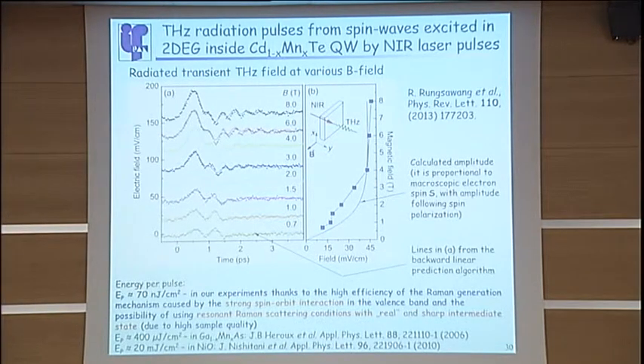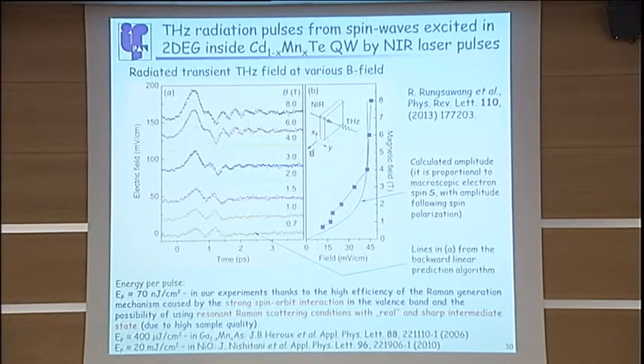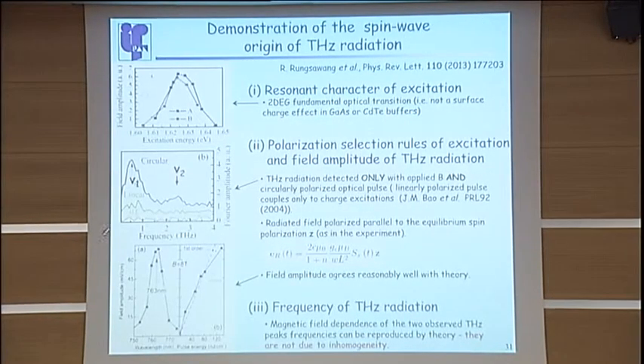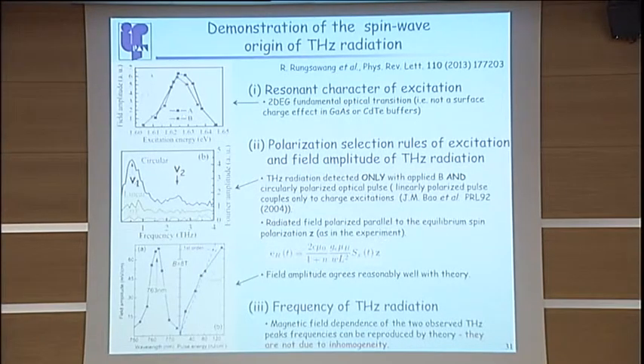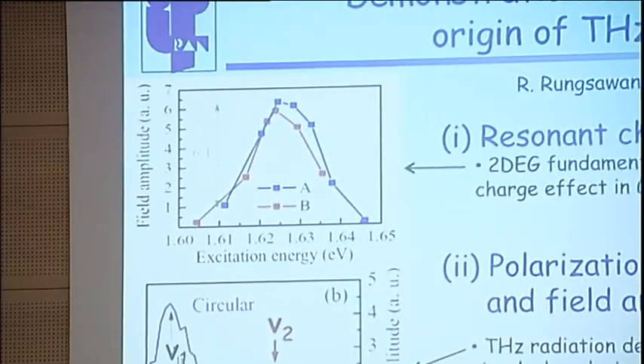Please note that in our experiment, done by our colleagues, the energy per pulse was orders of magnitude smaller than in other cases, because we could use a high efficiency Raman generation mechanism, and also the possibility of using resonant Raman scattering, which coincided with real and sharp intermediate states, due of course to the high sample quality. This resonant character was used to prove that this really comes from the 2DEG, not, for instance, from surface charge effects or from buffers, because the energy coincides with the energy of fundamental transitions.